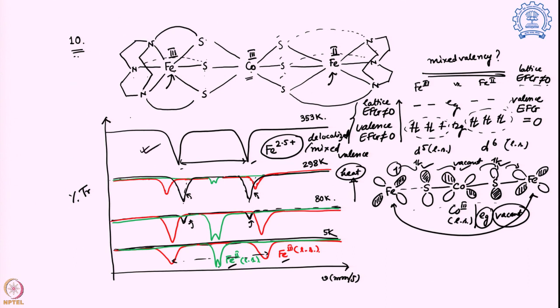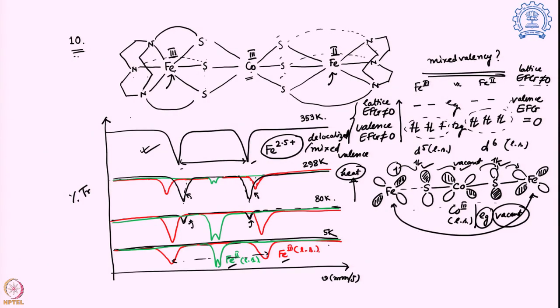But as we start lowering the temperature, the iron centers stop interacting or exchanging, because at lower temperature the sulfur and cobalts are not that flexible, so that you can attain all the particular orientation you want to have for this electron exchange. And as we go further lower temperature at 5 Kelvin, where there is almost no interaction at all, you can say this mixed valence system is almost gone. However, it stays quite visibly even up till 80 Kelvin temperature.